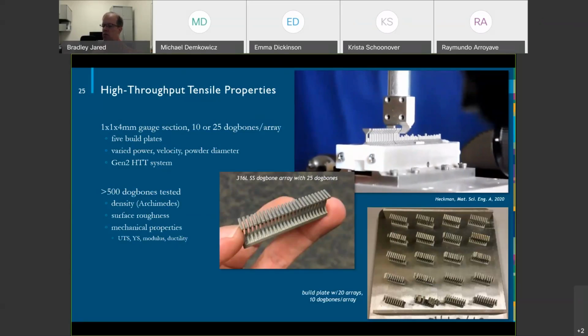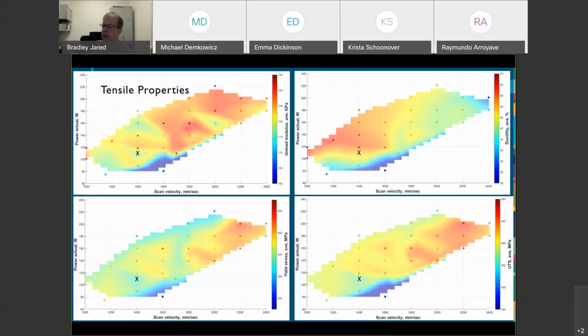We use this quite frequently. In the 4 years that this system has been up and running, we've printed and tested probably multiple thousands of tensile arrays. So we have a lot of data here. You can see what we need. And one thing that's nice about the samples is we can get things besides tensile properties: we get density, we get surface finish, all those things off the system. So when we take this and go back to our process map, one of the things we find is an understanding of where our properties lie in this material.